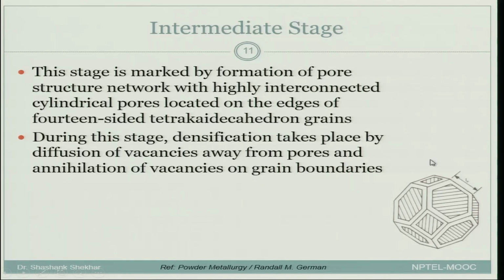Next we get to the intermediate stage, and this is characterized by this kind of shape. So, there are grains. This is a grain or a particle which has stuck to the other particle, and in between the particulates that it is attached to there will be a network of pores. These are long cylindrical pores that are forming a network. In a much simplified way, we can say it is a 14-sided tetrakaidecahedron grain in the much more ideal or simplified form.